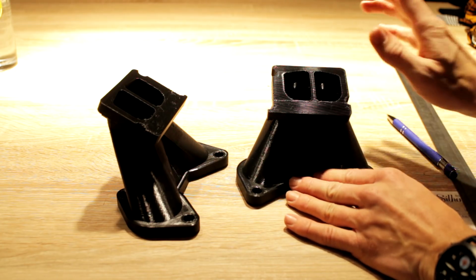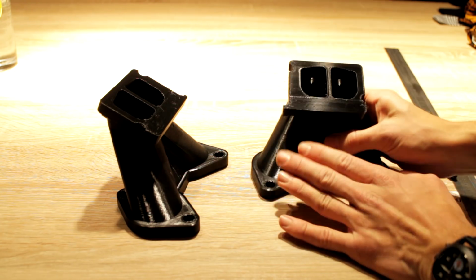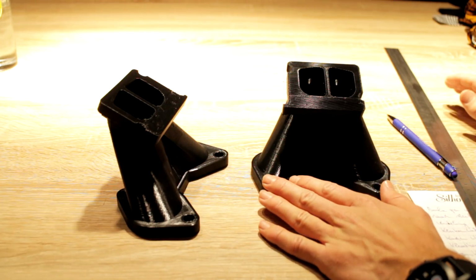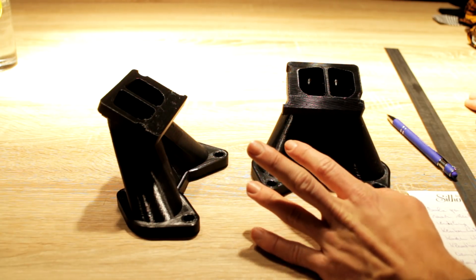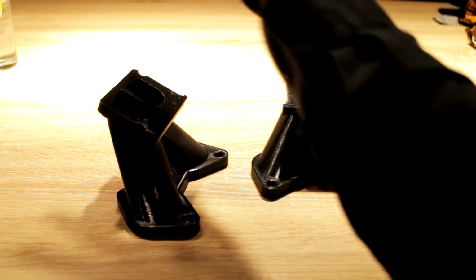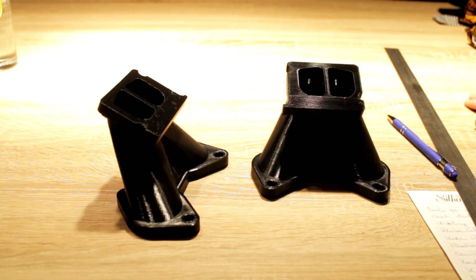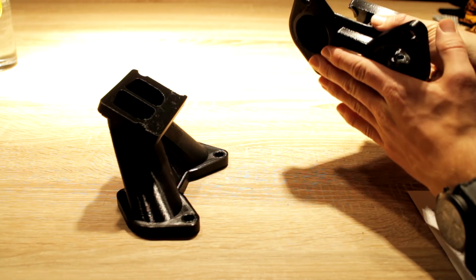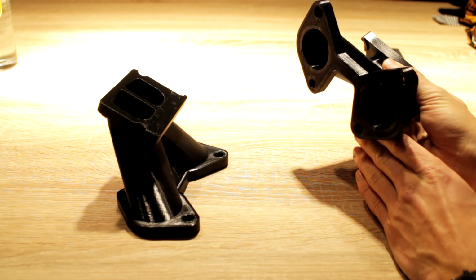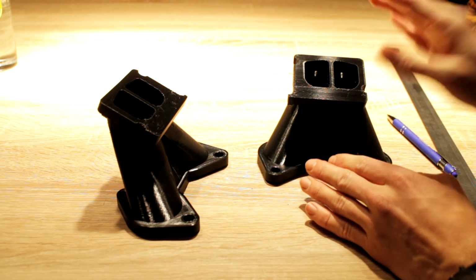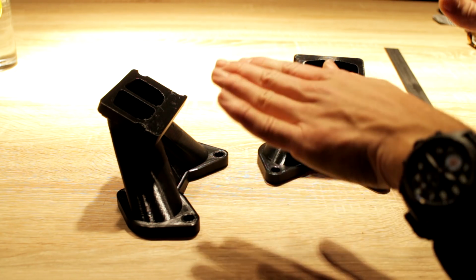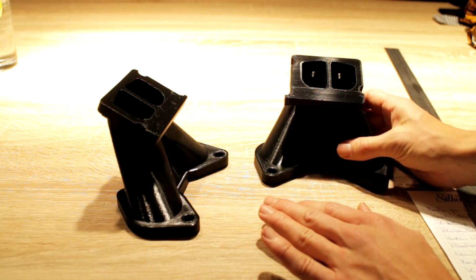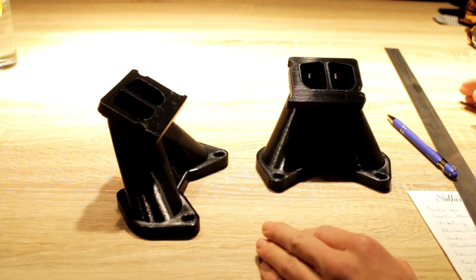the post-processing, I've put these in my oven on one of the plates that was included. What I didn't know is that the plate was bent a little bit from the heat that I've used when cooking, and both these flange surfaces have warped a little bit because once the first time it gets soft, it sags a little bit, and it just sagged to the shape of the plate.